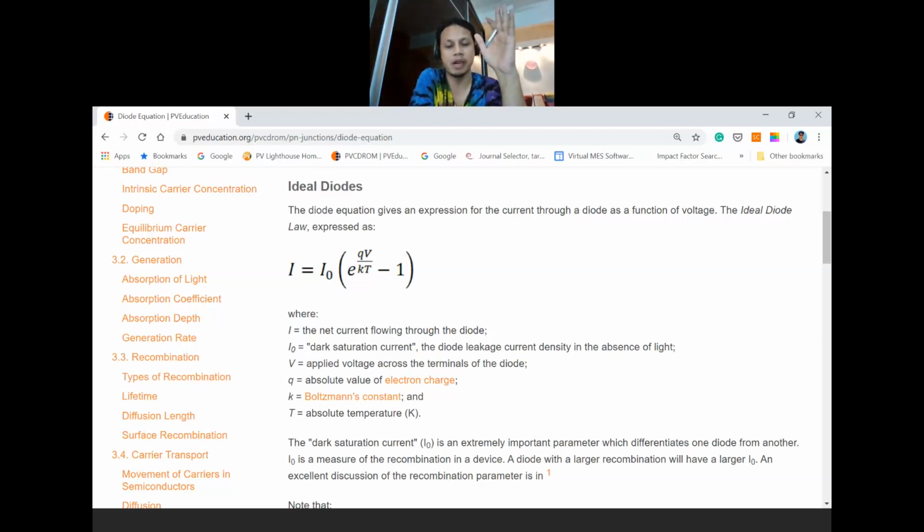In a black box, there's no light at all. You just put the probe on the negative side, put the probe on the positive side, and then you bias the voltage to the plus side and bias the voltage to the negative side, and then you can actually get the dark saturation current, right? So therefore it's called dark saturation current because it's measured in the dark, no light.